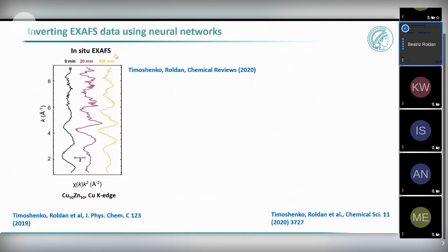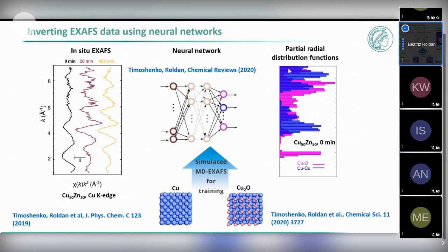This is here the XAFS data as a function of the reaction time. To analyze this type of data and get actual information about the radial distribution functions, which is very important to distinguish, for example, metallic copper from copper-zinc, we are using neural networks. You see here the neural network is trained using simulations. We have created a database of XAFS data using molecular dynamics.